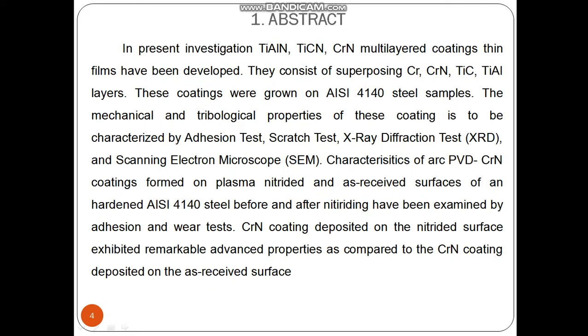First of all, abstract. In the present investigation, TiAlN, TiCN and CrN multi-layered coating thin films have been developed. They consist of superposing Cr, CrN, TiC, TiAl layers. These coatings were grown on AISI 4140 steel samples. The mechanical and tribological properties of these coatings are characterized by adhesion test, scratch test, X-ray diffraction test, XRD, and scanning electron microscope, SEM.